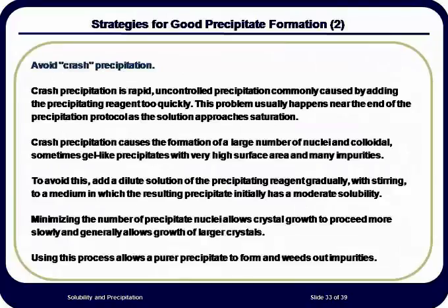Remember that to form better crystalline materials, we want to exclude impurities. When reagents are mixed rapidly and at high concentrations, a high level of localized supersaturation is realized. This will yield a floc that will trap soluble materials within it. To help minimize this crash precipitation effect, use dilute solutions of the precipitating agent, add it slowly with vigorous stirring, and gently heat the solution.